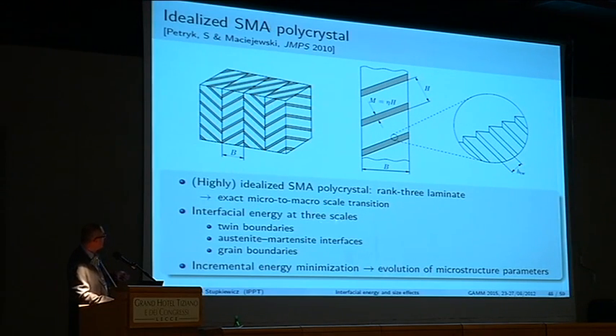So we consider interfacial energy at 3 scales. Starting from the bottom, we have twin boundaries here, the energy which we get hopefully from material science. Then we have the austenite twinned martensite interface. Here we have two contributions: atomic scale energy along the zigzag interface, and the elastic microstrain energy, the one that we predicted, that we computed. That's the austenite martensite interface, seen here already from the macro perspective, assuming some kind of scale separation. And finally, we have grain boundaries, at which again we have martensitic plates terminating at the interface, which means that again we have this elastic microstrain energy.